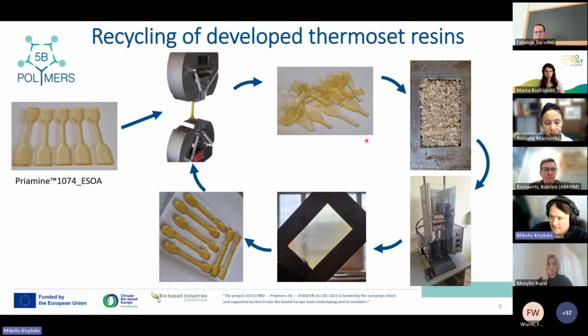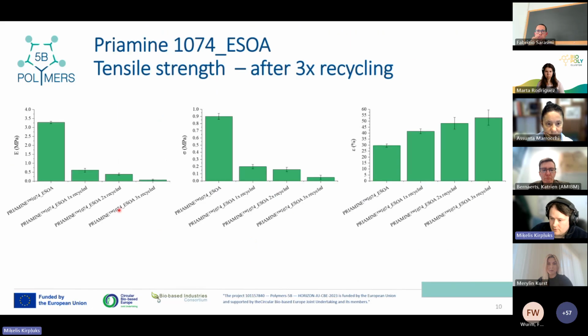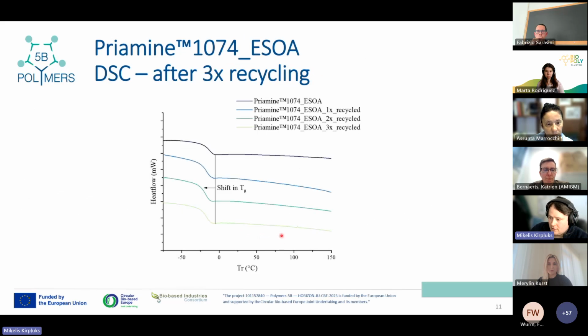So this is what we did for the aza-Michael thermoset resin based on bio-amine and epoxidized soybean oil, and we reprocessed them. But we ran into a problem. After every reprocessing cycle, our mechanical properties degraded quite significantly. There is a huge drop in tensile strength with every recycling step. And also the glass transition temperature shifted after the recycling of the material.